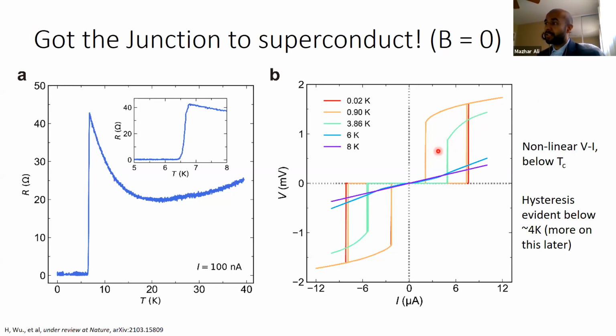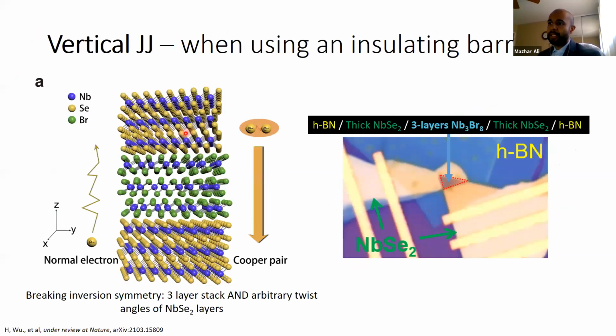And there was a lot of hysteresis as well. So we're going to talk about these characteristics in a minute, but the hysteresis is as expected because if you look at this, it's basically a parallel plate capacitor, right? We have 2 metals, superconductors, separated by an insulator. So you expect to have a capacitance. And if you have a capacitance, you expect to have a hysteresis. So that wasn't too surprising.